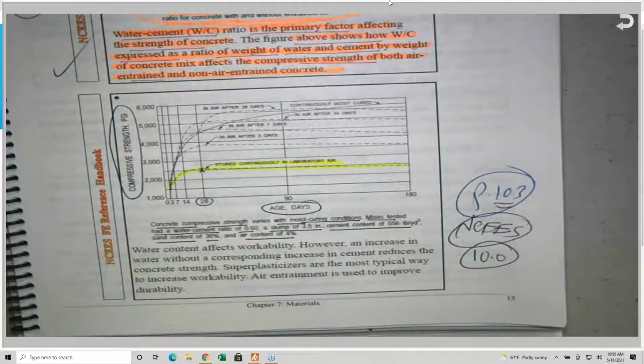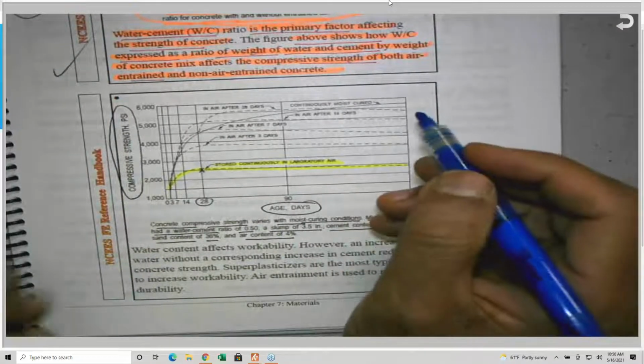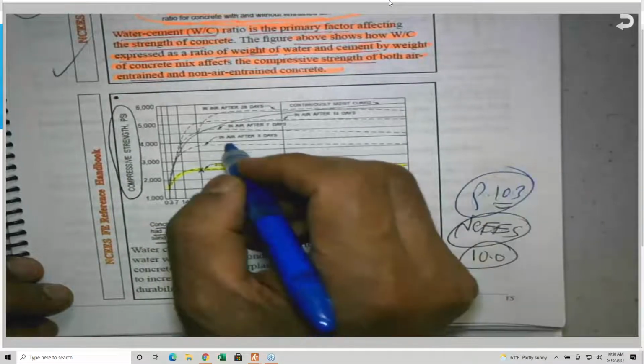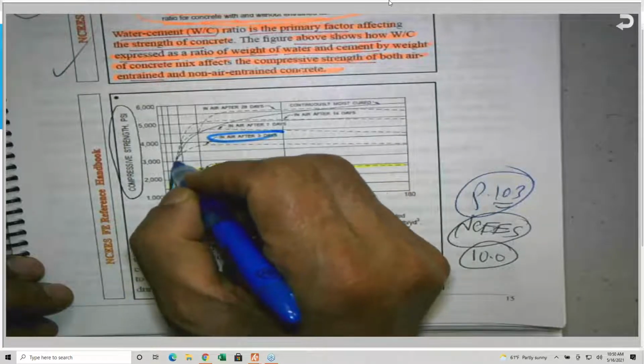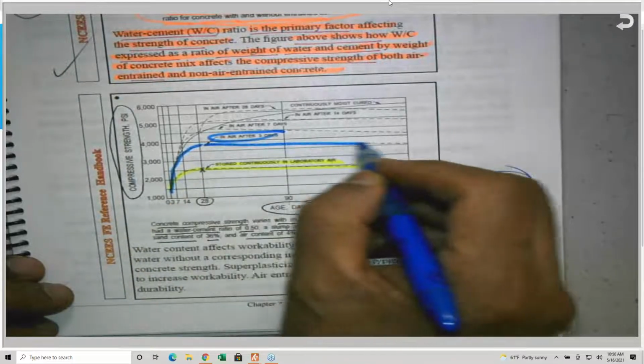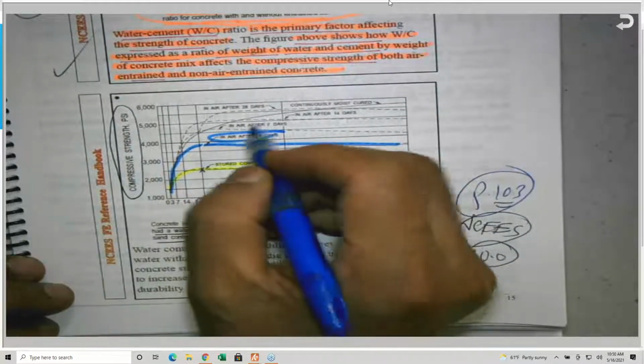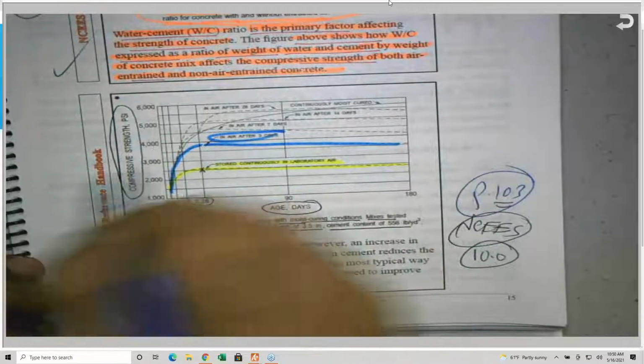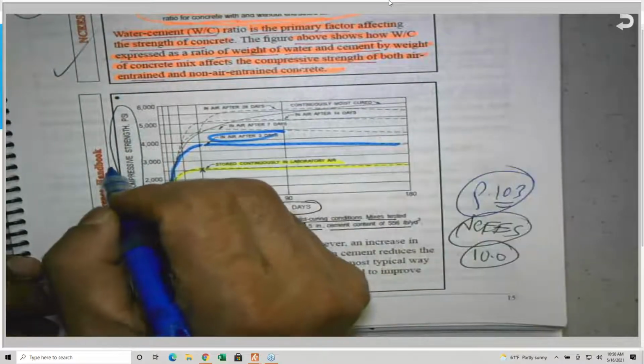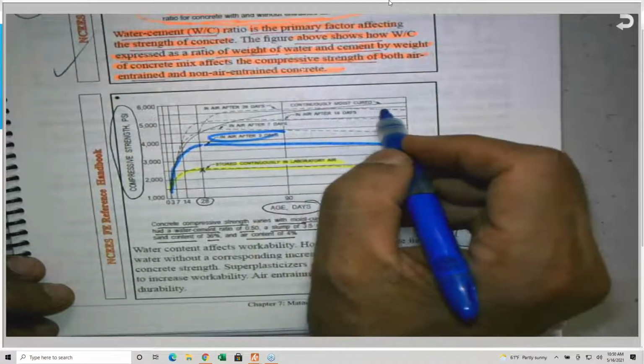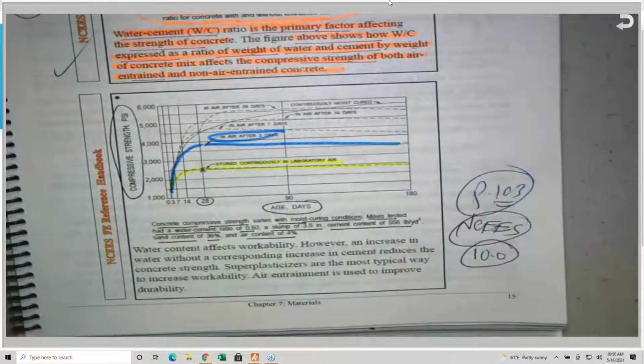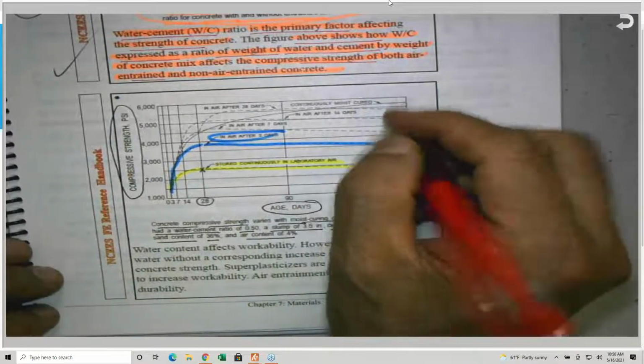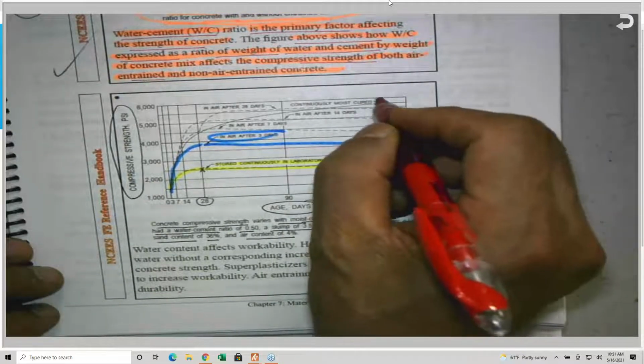But if you keep the concrete moist, and you put it in the air after 3 days, the concrete will increase the strength, but after that it levels off. Then in the air after 7 days, and in the air after 14 days, and continuously moist, which is the solid one, which is a very important one. And I will tell you why. If you look at the solid one, continuous moist, here it is, this one.